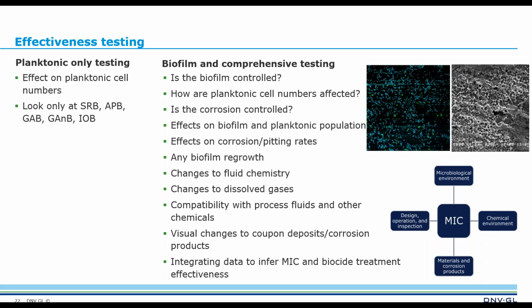The biocide should be tested to see if there's a possibility of biofilm regrowth, and changes to fluid chemistry after the biocide has been added should be investigated to see if there are more nutrient sources for the microorganisms, and whether after biocide addition there are indicators of abiotic corrosion, meaning MIC has been mitigated, and now all you're seeing is indicators of abiotic corrosion. Changes to dissolved gases are important to look for, and compatibility issues between process fluids, biocides, and other process chemicals are also important to consider.